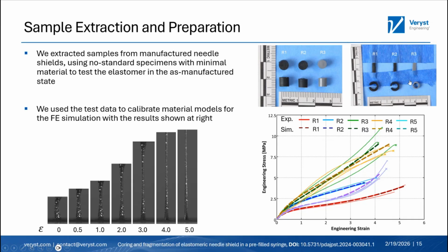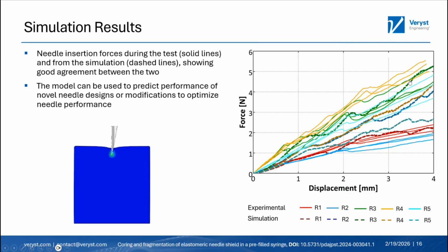With the match between the data and the test, we're then able to take that and perform a simulation. The final simulation that we are running is this needle coring simulation, which you can see on the left. You can see a needle made of metal that is being pushed into a cylinder. This is shown in 2D, but this is a 3D simulation. We're just showing that cut face right there. The colors are the stress contours in the material itself. You can see there's a stress concentration at the tip of the needle, but then there's a little island of material that gets cut off and cores the needle due to some cutting that's going on in there. And then it sits there. That's the phenomenon that we are investigating and trying to understand and predict the performance of. You can see that we're predicting it there.